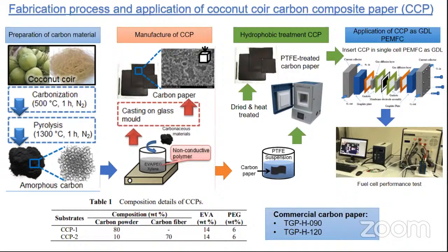In this work, two types of CCP were made with different shapes of carbon. We can see the composition details in this table. Okay, to improve the hydrophobic property, both types of CCP were treated by dipping in PTFE suspension, the hydrophobic agent, and drying, followed by heat treatment at around 350 degrees Celsius in air atmosphere. Then we apply the CCP in the single cell of the fuel cell to check the performance in the PEMFC system. This instrument is available in our laboratory.